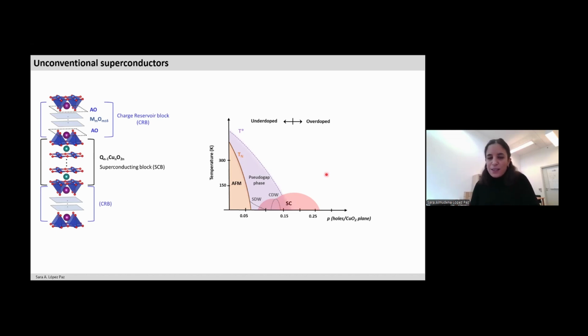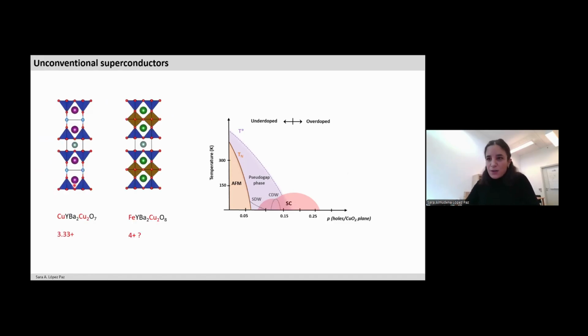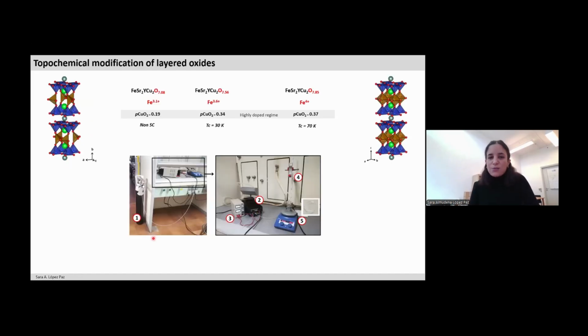And there is a simple reason for that: chemically it is very hard to access this region of the phase diagram. If we look at the prototypical YBCO compound, there is a maximum oxygen content that we can incorporate in the structure. And this means that there is a maximum oxidation state that we can reach, which is already pretty high for a copper atom. So our idea was, let's try to replace copper by another transition metal, which could eventually allow us to introduce more oxygen. And in order to force iron to adopt also a pretty high oxidation state, what we did is to try a low temperature approach using ozone as a strongly oxidizing agent that we were generating in situ. And in this way, we were actually able to increase the oxygen content almost up to 8 and stabilize still superconducting materials at very high doping levels.